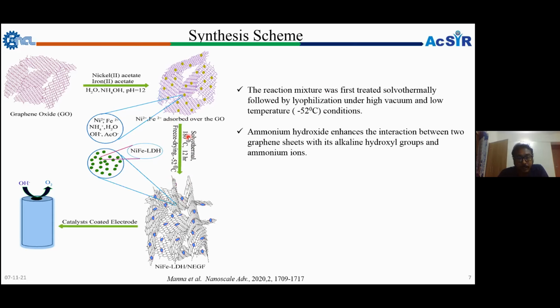So first in this hydrothermal or solvothermal treatment, metal particles nucleate over the nitrogen doped sheets, because in the presence of ammonia, nitrogen can be doped over the individual sheet, and nanoparticles of oxides or layered double hydroxide grow over the particular sheets, and the structure will be retained because ammonium hydroxide at a particular concentration makes a self assembled structure form. So only by applying the freeze drying, water could be removed, and then the 3D structure will be retained. So the final product is the nickel iron layered double hydroxide supported nitrogen doped entangled graphene framework. Further we used it for the electrochemical performance measurement for oxygen evolution reactions.